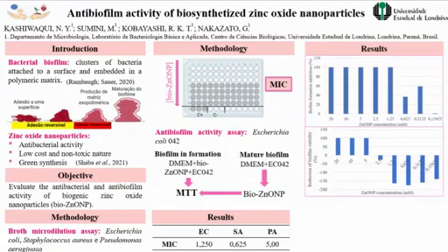The zinc oxide nanoparticles can prevent the initial adhesion of the bacteria to the surface, impeding the biofilm formation to start, whereas the presence of the exopolymeric matrix in the mature biofilm protects the bacteria against the nanoparticles, being necessary a higher concentration of zinc oxide nanoparticles to completely eliminate the mature biofilm.